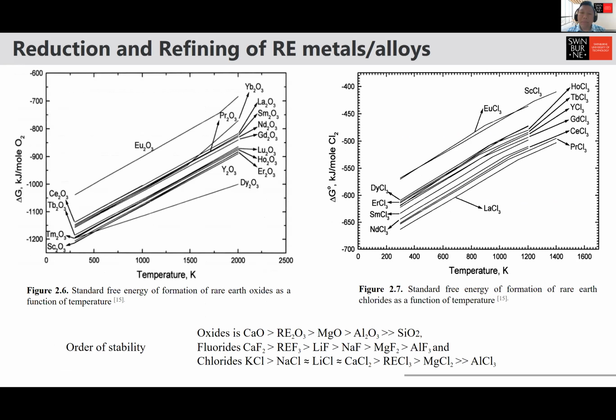So this is what I was talking about earlier. The picture on the left is the standard free energy of formation of different types of rare earth oxide as a function of temperature. This, in a sense, is basically an Ellingham diagram for oxides, if you remember. You can see from here that these different rare earth oxides have a similar value of delta G formation, particularly the ones in the middle. That's why it is very difficult to separate some of them, for example lanthanum from samarium, lanthanum from neodymium, or from gadolinium, because they all have similar delta G.